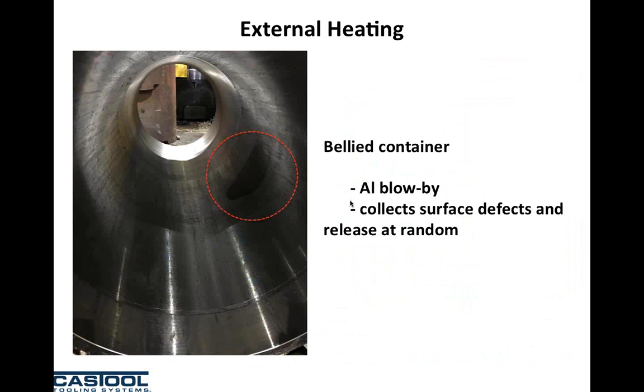This is a typical container that's being relined, and you can see where it's been bellied in the one part. We'll talk about it a bit more in a couple of slides, but the interface between your dummy block and the liner is very sensitive, and the gap between your dummy block and your liner is very similar to the aperture in the die. So if this gap is increased, you're going to have a maximum blow-by. The other problem is these areas of bellying tend to collect the oxides and inverse segregation in your billet. And as they're collected in these depressions, they can be released into your profile randomly.